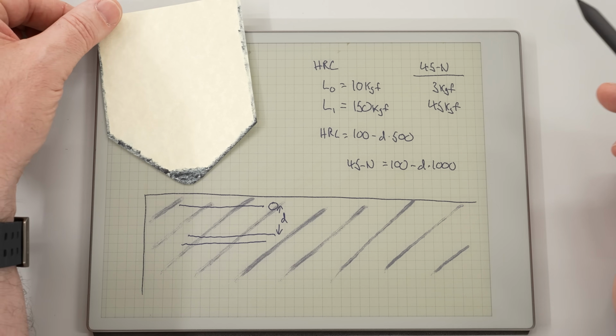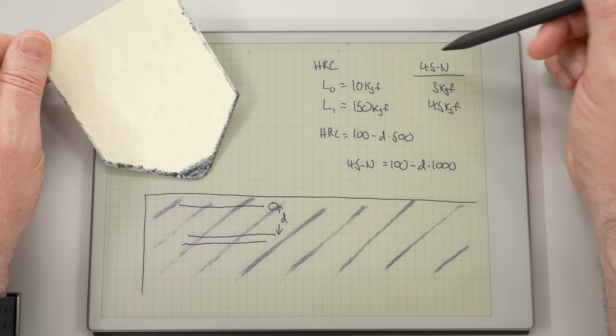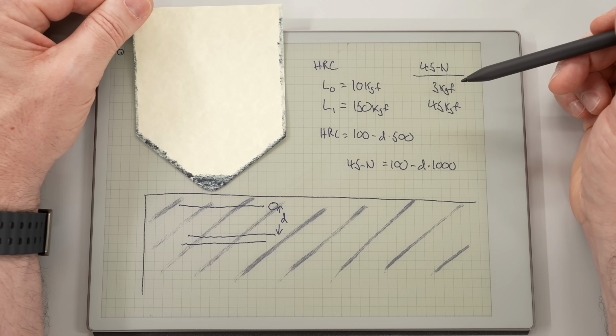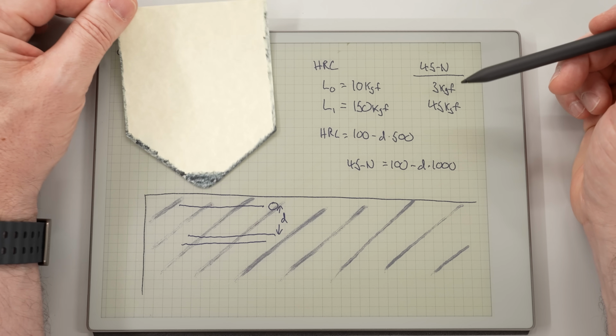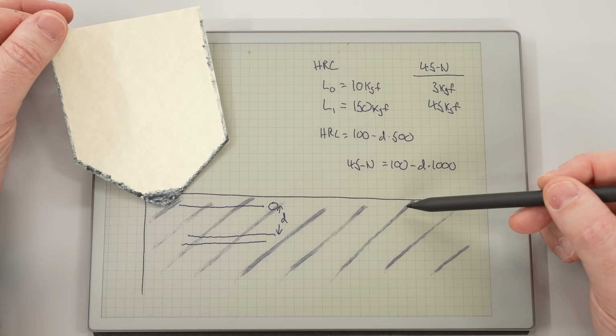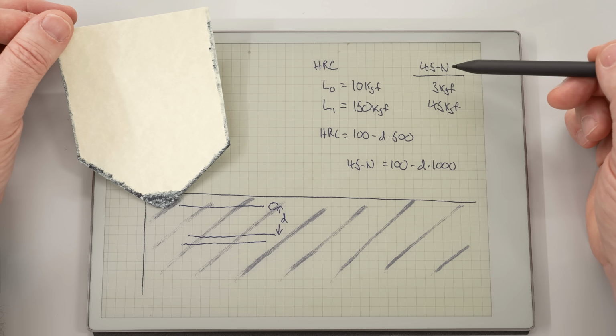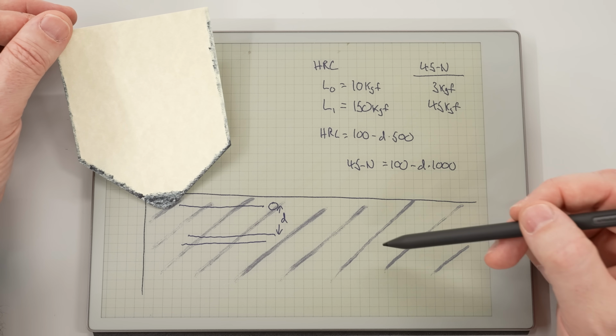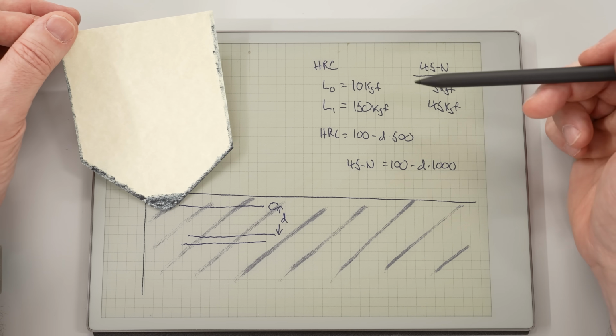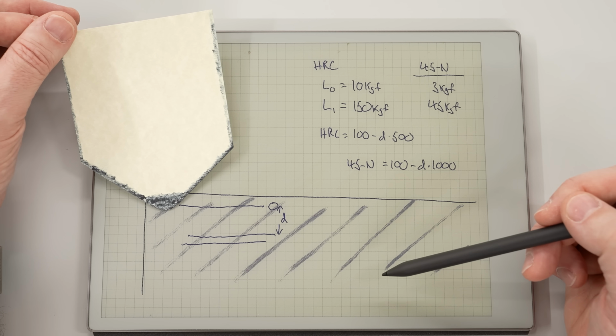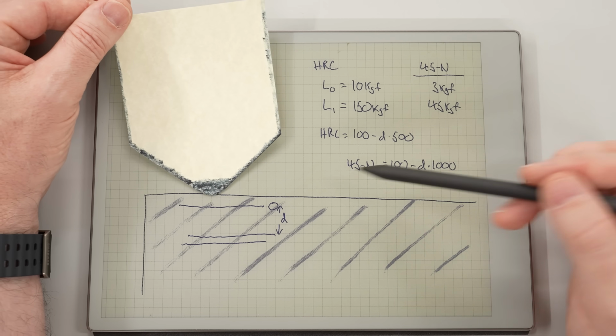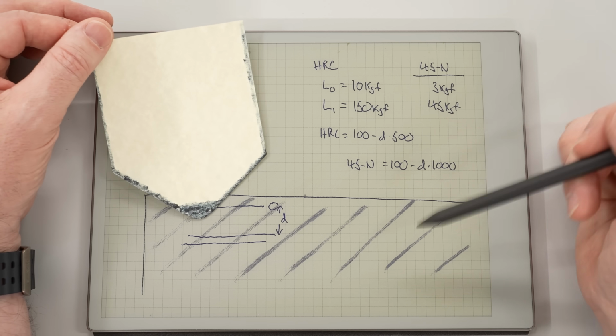There are some caveats. The 45N, this is a superficial hardness, so it's only measuring near the surface of the part. So if you have a case hardened part, this is going to usually measure the hardness of the case, not the interior. If your part is through hardened, then it doesn't matter, because the hardness of the surface is the same as the hardness of the interior.